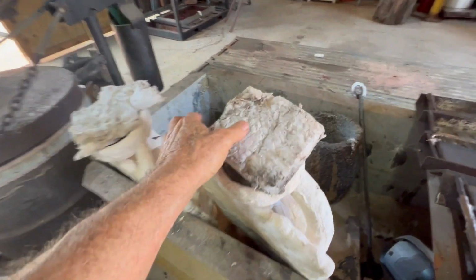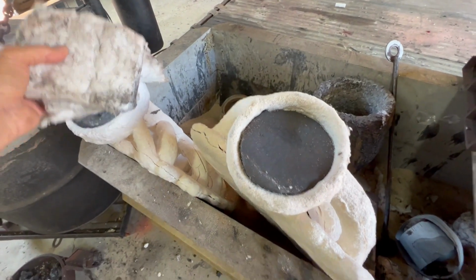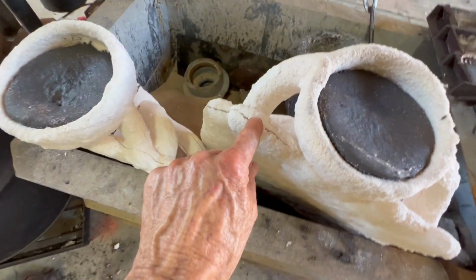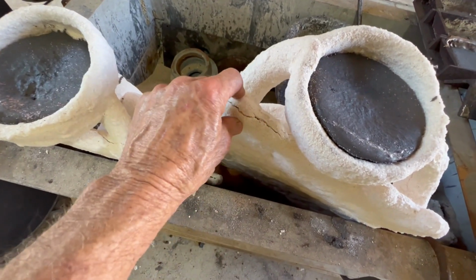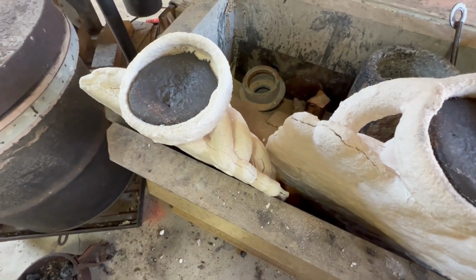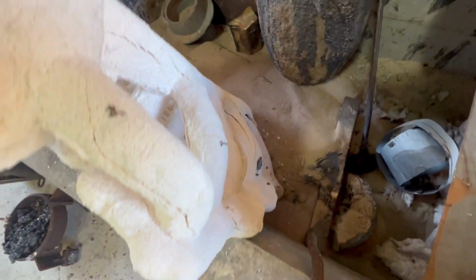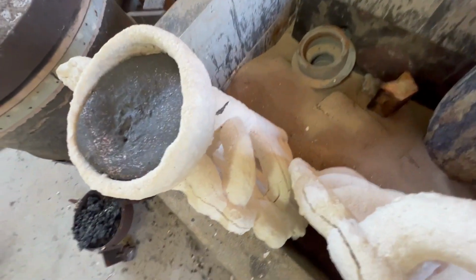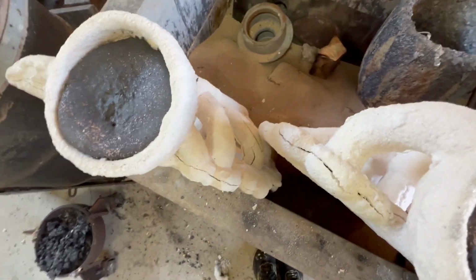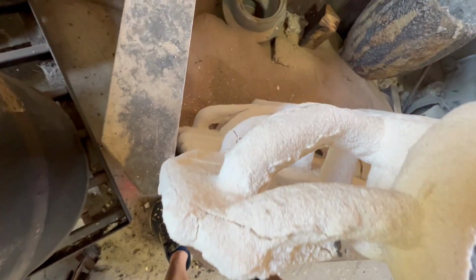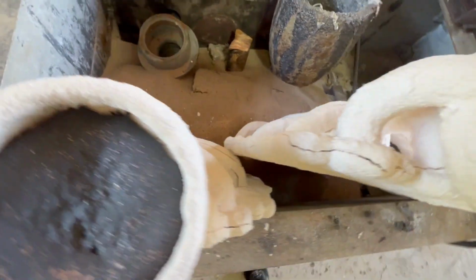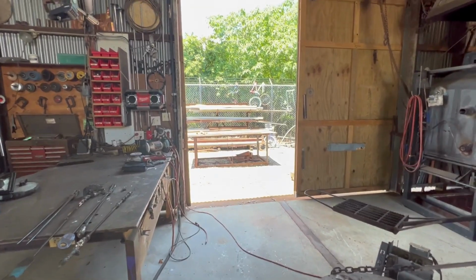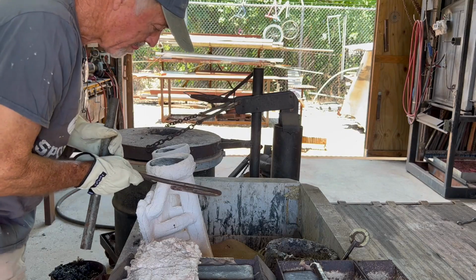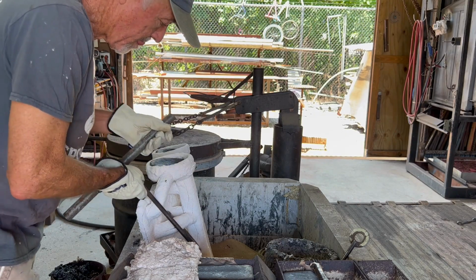Okay, back to the current project. The bronze was poured probably 30-40 minutes ago. It's starting to cool, and when the bronze cools it shrinks. The ceramic shell does not shrink or expand with temperature, so you get some stresses built up and the molds crack, and that's actually a good sign. That means our bronze most likely filled all the way to the top when you see the cracks at the top. Taking it outside so we can break the shell off of it.